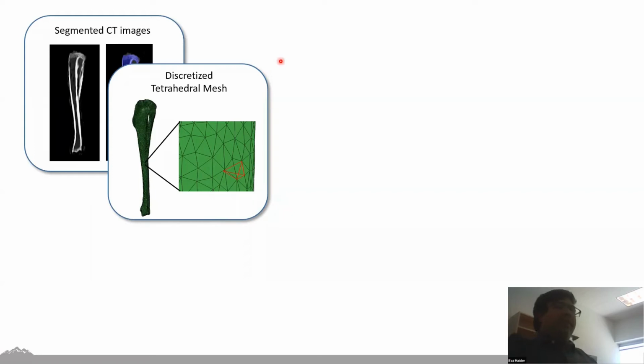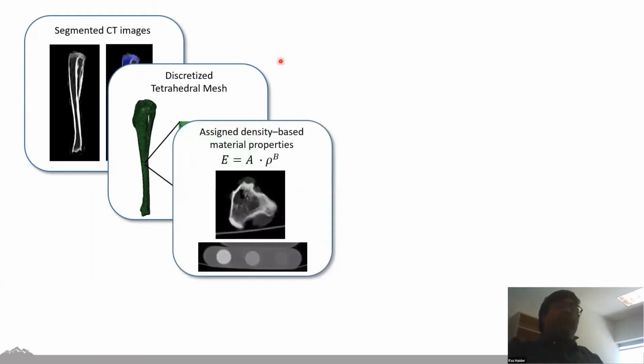But I'm getting a little ahead of myself here because after we discretized the mesh, there was still one important step to do, which was we assigned material properties to our model. In our case, we used heterogeneous material properties that were based on local CT measurements. And you can see the reason why that might be necessary when you focus on this cross-section of the tibia that I'm showing here. As you can see, some parts of the image are very bright, indicating that the bone probably has a lot of density. It's probably very stiff over there. There are other parts of the image where it's not very bright, it's a lot more dim. And that would seem to suggest that there's less dense bone in that region. And so we expect that bone to have a lower Young's modulus.